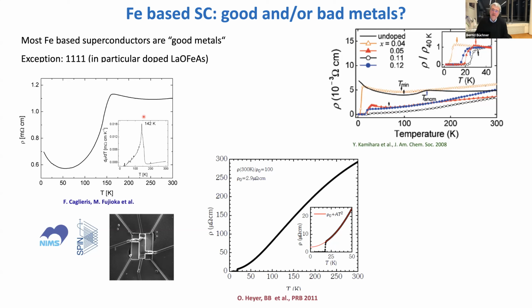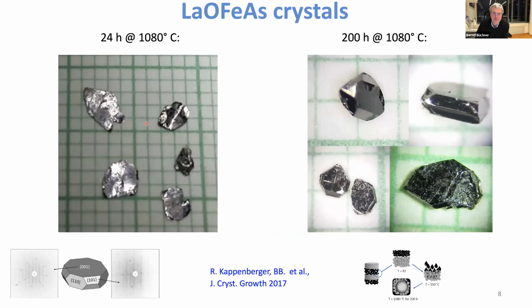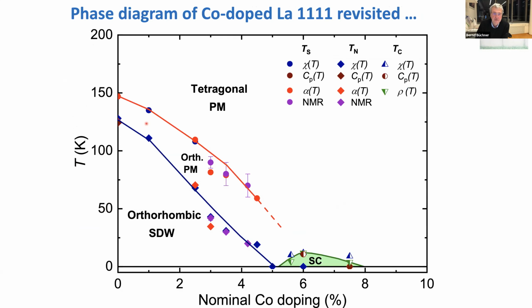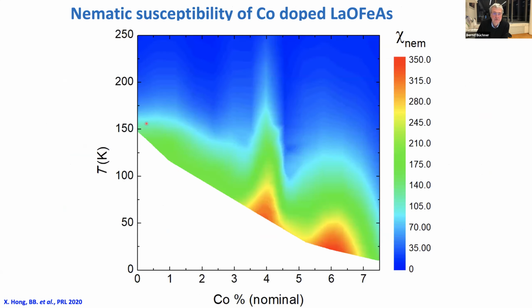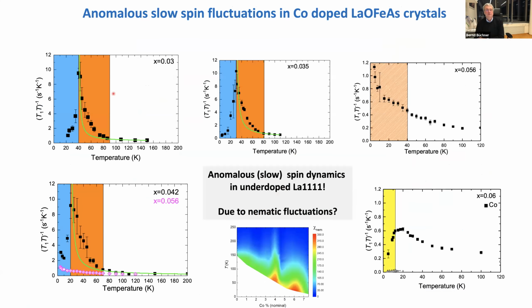Okay, now the glassy behavior. Of course, we have the NMR, and for the NMR I did not push that a lot. So you have these long-range order phenomena, but on top there is of course some kind of short-range order going on. It's a little bit glassy, at least short-range ordering. Let's call it that. Maybe it's connected to, or appearing close to, the quantum critical point for magnetism.